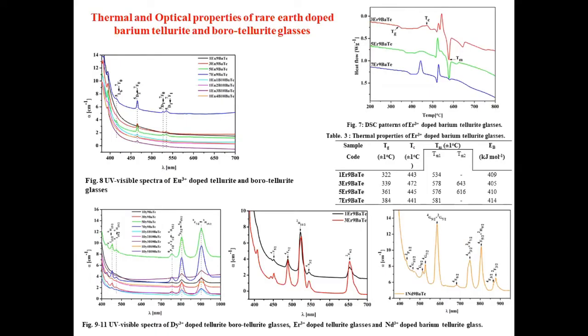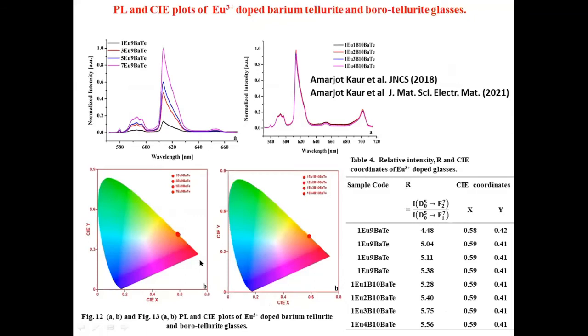We can dope rare earth ions like erbium in barium tellurite and barium borotelluride glasses. Rare earth ions are needed to cause fluorescence in the tellurite materials. And these are the optical absorption spectra, the three patterns at the bottom. And these are the DSC patterns for erbium doped barium tellurite samples. And again, erbium doped samples emit green light, whereas the europium doped samples emit red light.